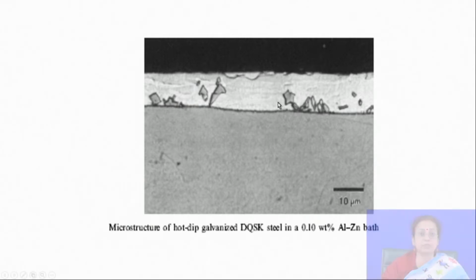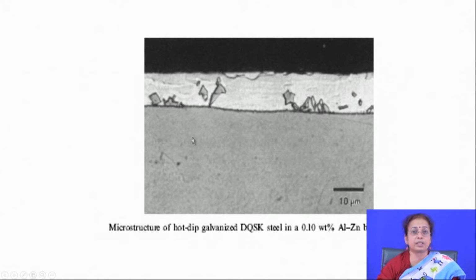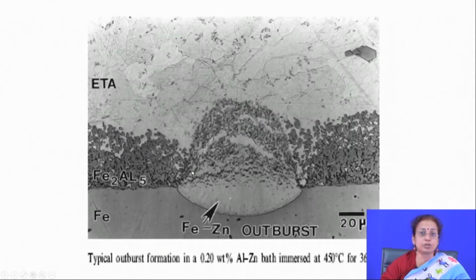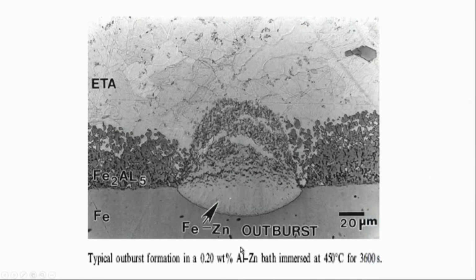In the case where you have normal galvanizing with 0.1% aluminum, you will find that intermetallic formation is partly reduced. On the surface there is zinc coating, and at the interface there is Fe2Al5 phase, and the thick monolithic intermetallic formation is reduced. For example, this is the case of a galvanized coated microstructure with 0.2% aluminum. Here you will find that at the interface there is Fe2Al5 phase formation.